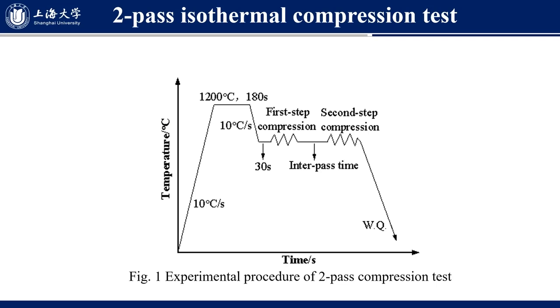Then, two-pass isothermal compression tests. The experimental procedure of the two-pass compression tests is conducted according to this plan. The steel was heated to 1200 degrees C, kept for 180 seconds, cooled to the deformation temperature, and deformed in two passes with different interpass times. After deformation, the specimen was water quenched as fast as possible to room temperature.